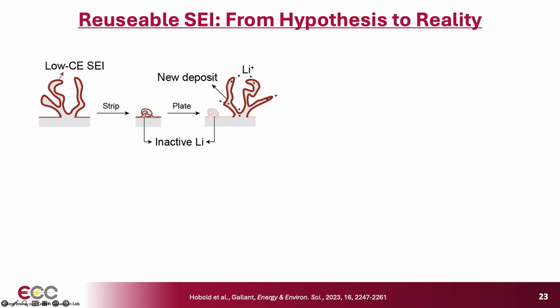And so you actually cannot use it. And so you have to kind of renucleate and grow a new lithium deposit alongside. And so you wind up with relatively low Coulombic efficiency because you have to reform the entire surface. And that corresponds to the low J naught values.